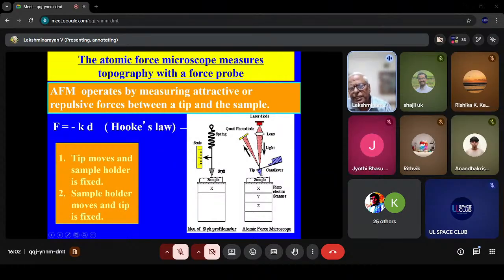Classically, diamond was used initially, but now silicon nitride tips are used, because the tip has to be very hard. It is going to scan over the surface, and in the process, it should not get deformed. Over it there will be some platinum or gold coating, and then a laser will be focused on that, and the laser beam will be reflected.